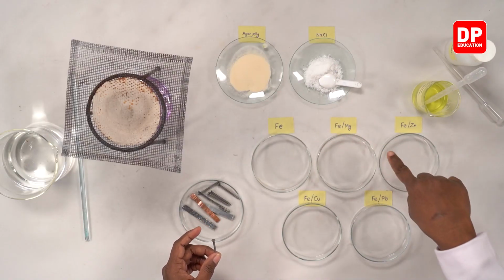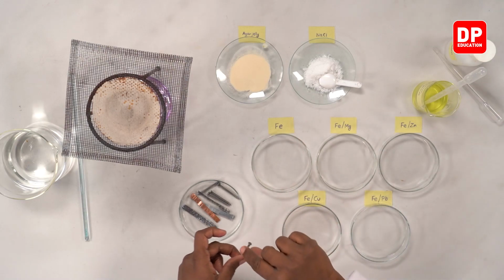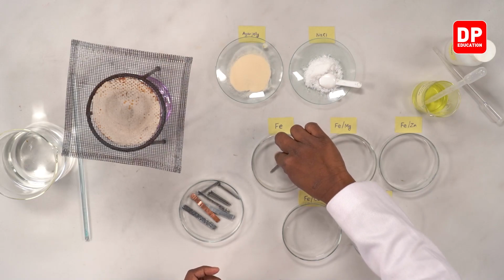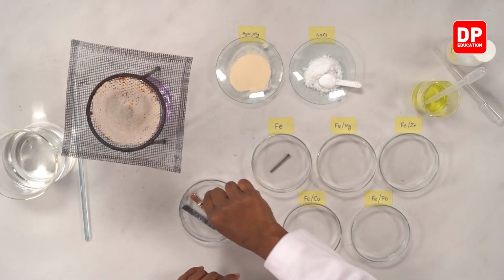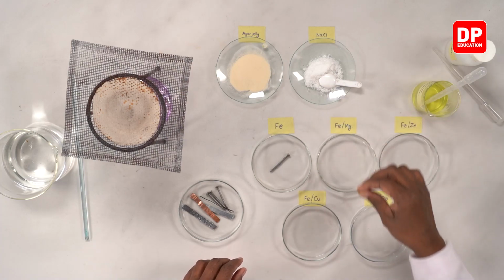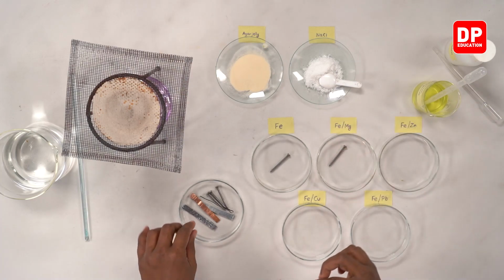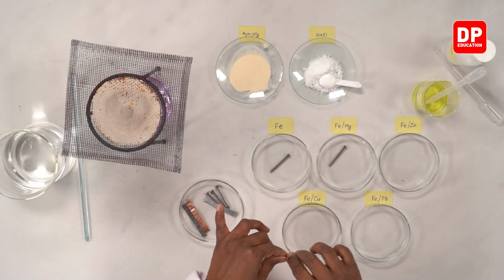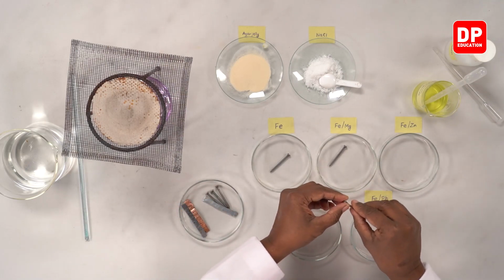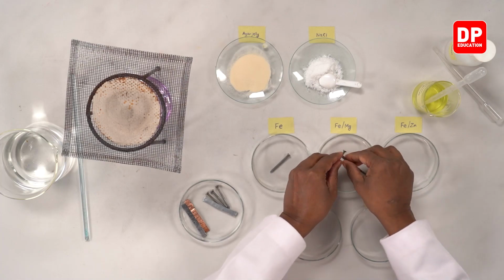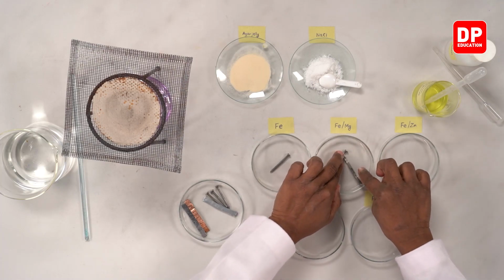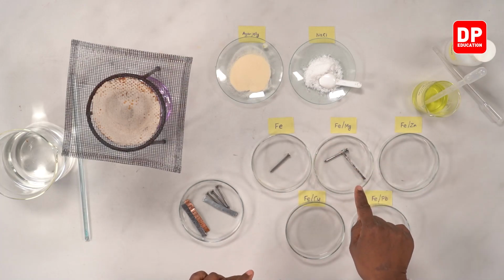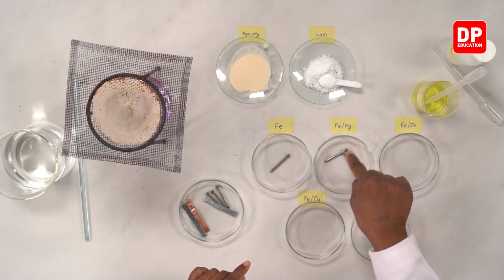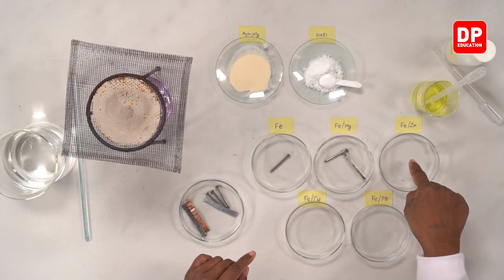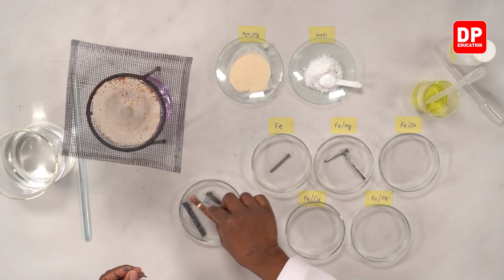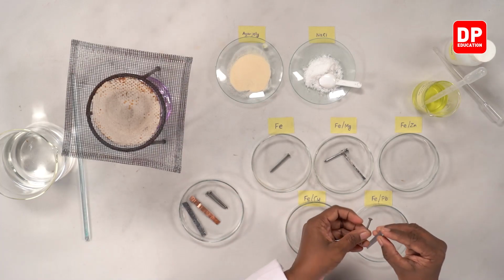So what I'll be doing first is setting these iron nails inside these 5 petri dishes. I have labeled them as well. Here you can see the first petri dish, it's only going to have the iron nail. Then the second petri dish, it's iron and magnesium. I'll be placing the iron nail and on that I will place the magnesium so that it is very much in contact with the iron nail. You have to place the second metal so that it is very much in contact with iron. Then I have iron and zinc, the third petri dish.